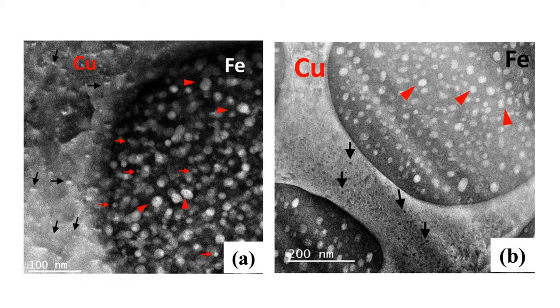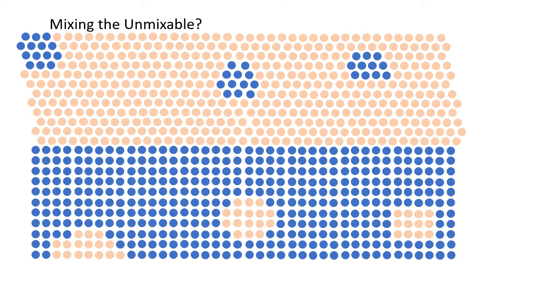If we zoom even closer in, though, we start to see something very interesting, that within the iron-rich regions, we have these light dots, which appear to be made out of pure copper. And within the copper region, we seem to have these dark regions, which seem to be made out of pure iron. This is counterintuitive because these two metals should try to separate as much as possible, but even within the seemingly pure iron phase, we were able to capture some copper, and within this seemingly pure copper phase, we were able to capture some iron. When we actually look at the atomic arrangement in these little regions, we see that it appears that we're getting hexagonal regions of iron within this hexagonal copper, and maybe even some cubic regions of copper within the larger cubic iron.